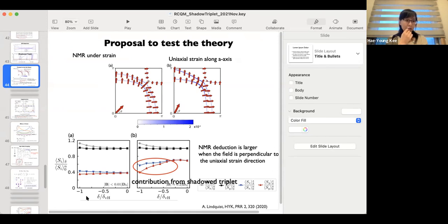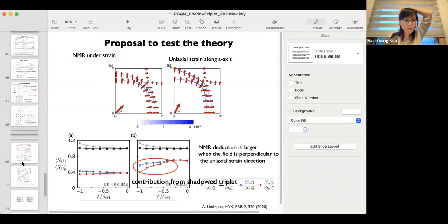At zero temperature, that will depend on the gap, and I didn't talk about the pairing symmetry, which is another big question. So imagine that I have a gap. If I had just the atomic spin-orbit coupling, in fact, I will have a very anisotropic quasi-particle gap. And in that case, I will not have any residual susceptibility. Okay.